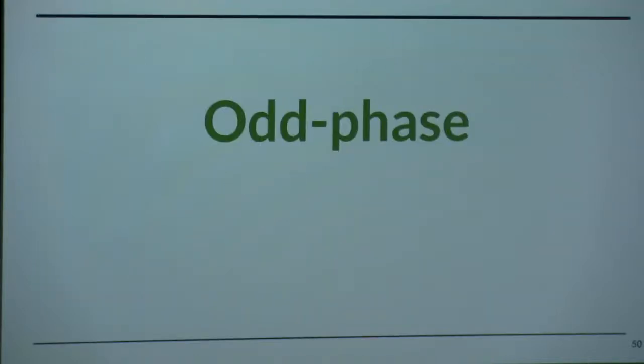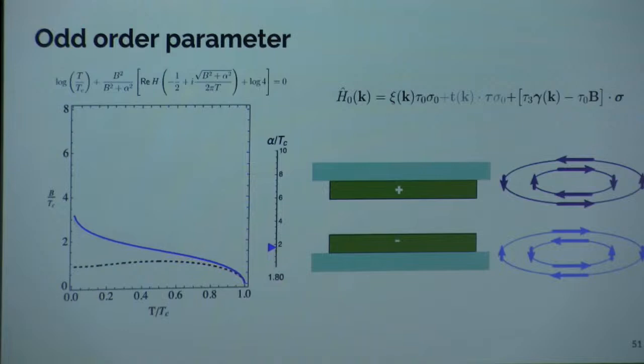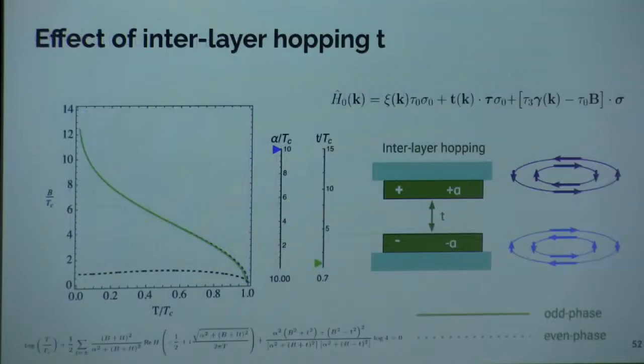Now, let us repeat the same exercise, but for the odd phase. In the odd phase, the only difference is that one layer has a plus order parameter and the other layer has a minus order parameter. Up to now, everything is identical to the even phase. Now we couple the layers. Here, the dashed line is still the even phase for comparison purposes, and the new odd phase is shown by the solid green curve. So you see that the solid green curve has a Tc that is suppressed.